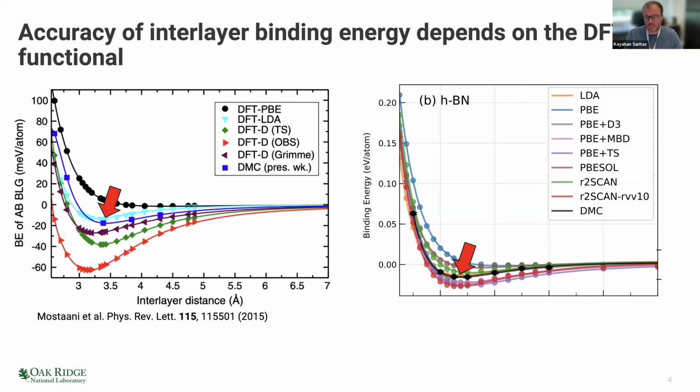And on the right is the result of the hexagonal boron nitride binding energies with respect to DFT and DMC. The DMC energies here are extrapolated to the infinite size limit. So you're seeing what we would see at the end of completing all the calculations presented in this workflow. This is an essential problem because, as Paul and others have talked about, we are trying to get accurate van der Waals interactions. This is a strong area for diffusion Monte Carlo, where DFT approximations might fail and may not exactly capture these weak interactions.